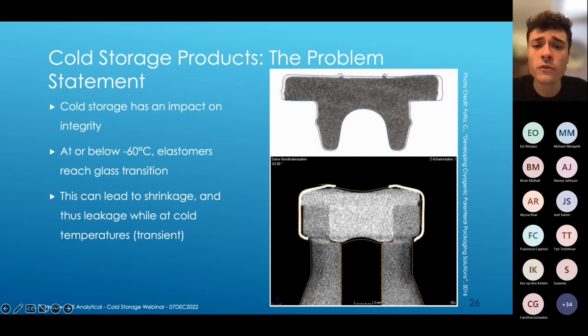And so I have some photos here from some work that was done by Chris Folta at Janssen back in 2016 and presented that highlights this. So this top image here is a depiction of what happens to this stopper when we're at room temperature, which is the outline, and then once we're at or below the glass transition state of that elastomer. And so you can see physically that this elastomer has shrunk. And so when that's part of a compressed package system, the same thing happens. And this second photo here shows exactly that, but the stopper applied and crimped down to a vial that is being brought down to ultra cold temperatures or deep cold temperatures. And again, you see that the stopper has shrunk a little bit relative to the vial and the crimp seal.